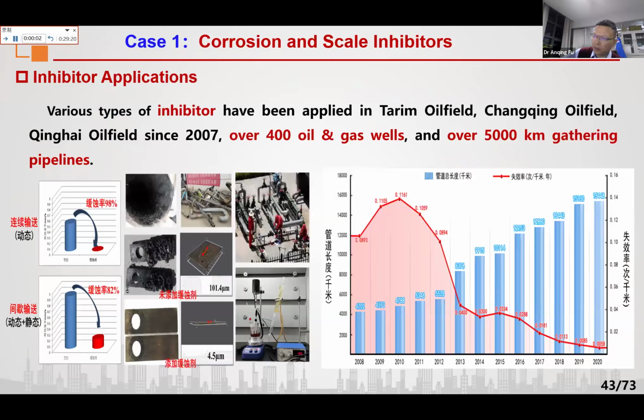The inhibitors have been applied over 400 oil and gas wells in Changqing, Tarim, and Qinghai oil field, and as well as in the gathering system, we applied over 5,000 kilometers gathering pipelines. The corrosion in downhole and the ground gathering system was greatly reduced by the inhibitor we developed, especially in the Tarim oil field, which is the third biggest oil field in China.